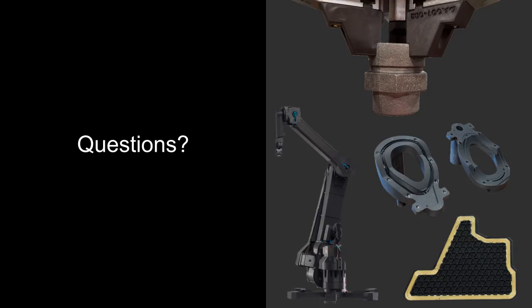Question on, do the two materials mix when printed as a composite, or are they two different prints? So how it works is, as I mentioned, the thermoplastic prints layer by layer, and that fiber is also laid on top of that. So it's not a mixing as much as it is a printing from one nozzle and then from the other nozzle to lay in that geometry that you're looking for.